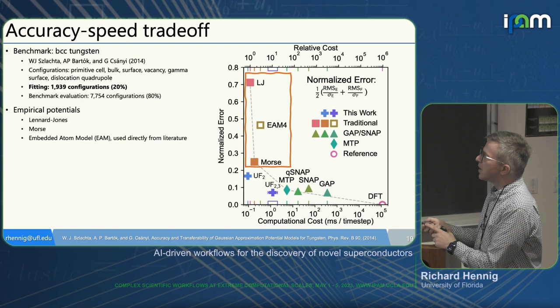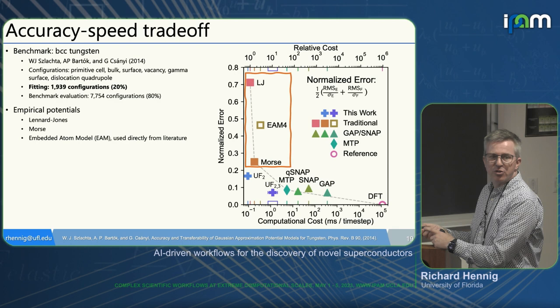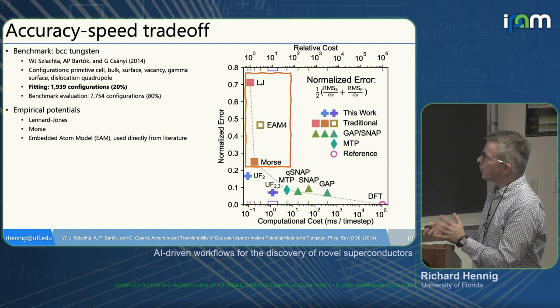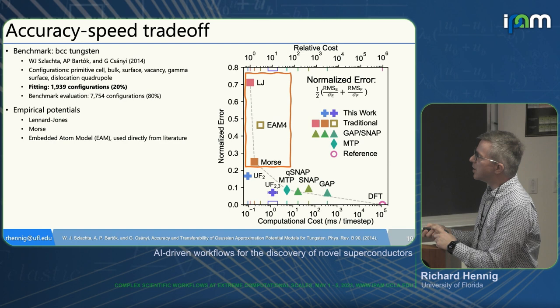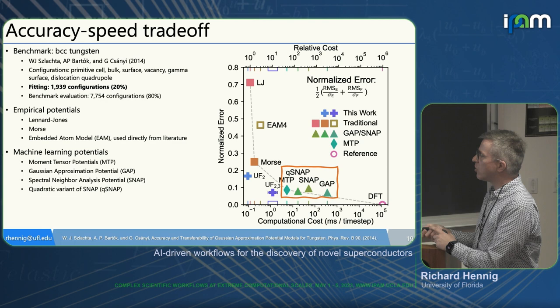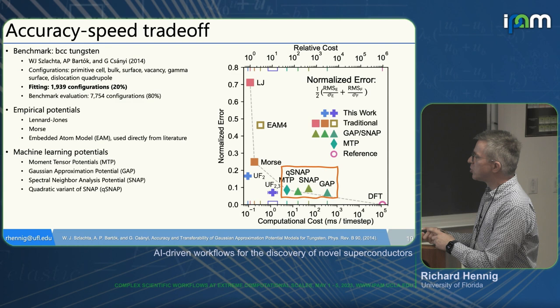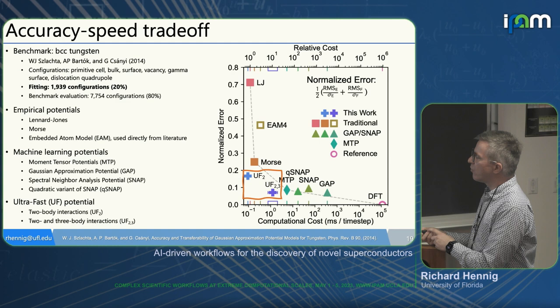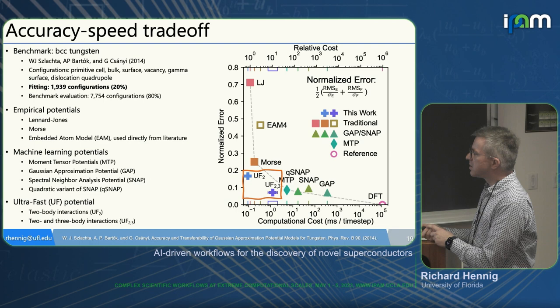The EAM potential we couldn't get a good fit for — it's still more of an art to fit a good empirical potential. For Morse and Lennard-Jones, those are simpler — fast potentials, great for MD of large systems, but error bars may not be useful. Current machine learning potentials fix that error. The moment tensor potential is a little faster; SNAP and q-SNAP are quite accurate; GAP is more accurate but reasonably expensive. Our ultra-fast force field with just a two-body term is actually slightly faster than Lennard-Jones. Adding the three-body term gets significantly more accurate — on the same scale as other machine learning potentials — but still has one to several orders of magnitude gain in speed.